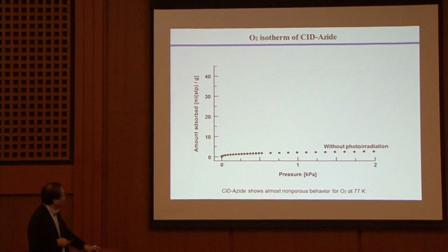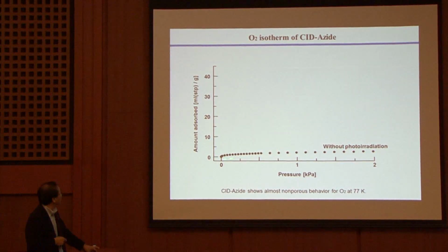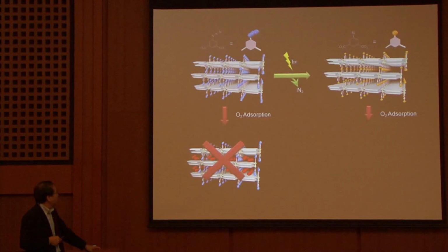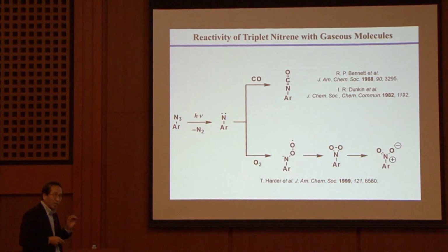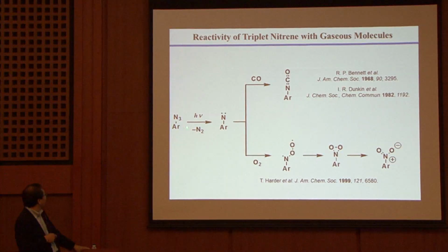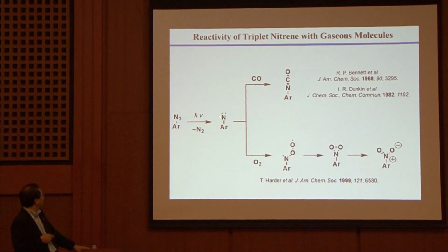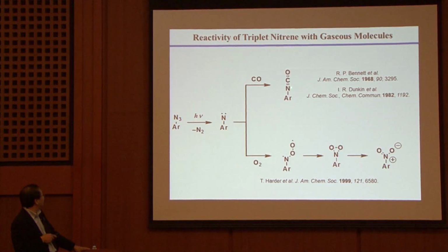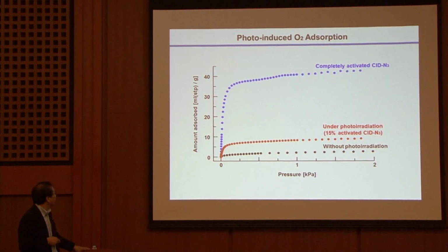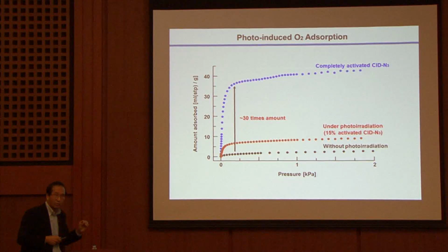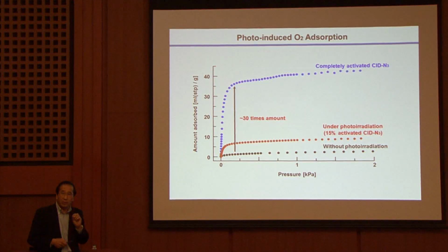And we tried oxygen adsorption. This is the initial precursor system. Of course, oxygen cannot be adsorbed in the cavities. Then we irradiate this material in the presence of O2. But please look at this. When we irradiate, the nitrene is generated, and then in the presence of CO, this gives NCO. With oxygen it gives NO2 or NO. This is the result. At 15% yield of the nitrogen, adsorption is like this. At 100%, oxygen is absorbed, even for very tiny amounts of oxygen in the gas, and only oxygen is trapped in this case.